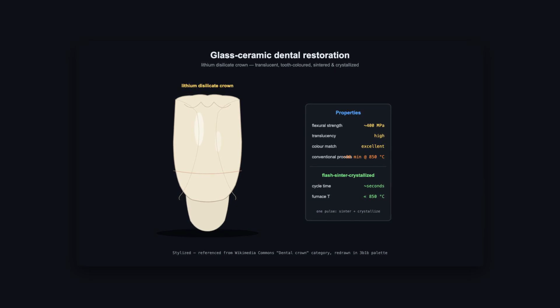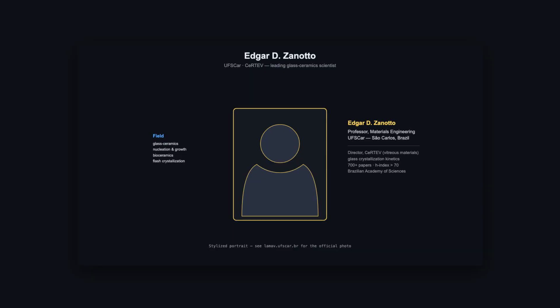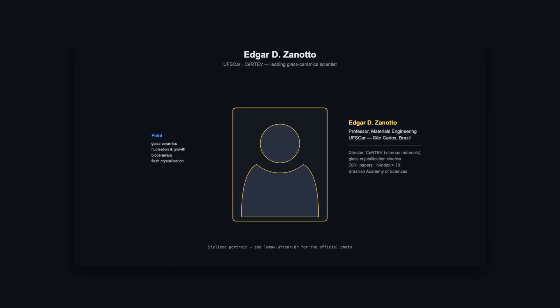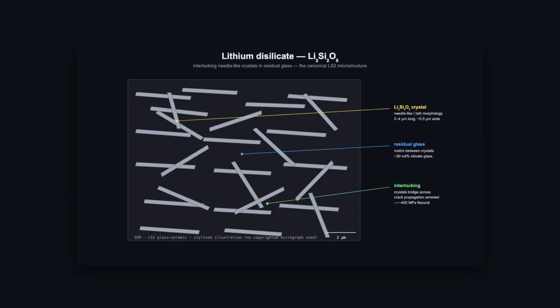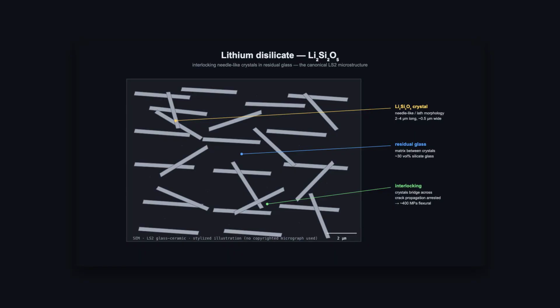In 2024, the São Carlos group came back with a second paper. Campos, Lavagnini, Rodrigues, joined this time by Edgar Zanotto, the world's leading glass ceramic scientist. Their target, lithium disilicate, the glass ceramic at the heart of Ivoclar's Emax CAD, the standard material for permanent dental crowns. Conventional crystallization, hours at 620, then 30 minutes at 830. Their version, Power Ramp Flash Crystallization, does it in seconds, at 360 Celsius furnace temperature.